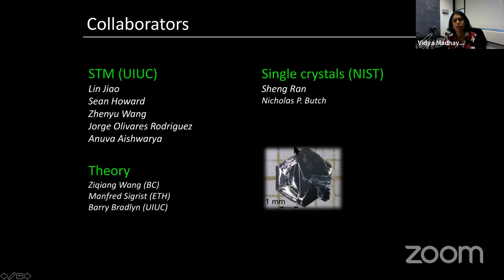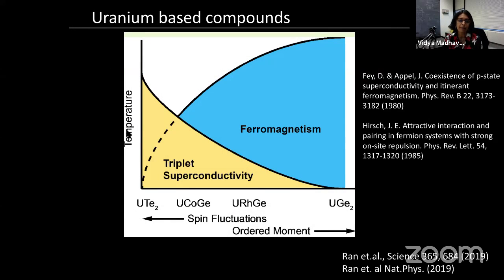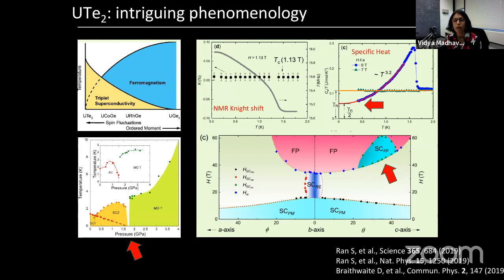The important thing here is that the material, uranium ditelluride, has been known for a long time as a heavy fermion metal. And it was only a couple of years ago that Sheng Ran and Nick Butch actually measured resistivity as a function of temperature below 1.2 Kelvin, and they saw superconductivity. So they made these beautiful crystals. They saw that it was superconducting, and that started a huge amount of excitement, mainly because uranium ditelluride is right at the borderline of being ferromagnetic. It's not ferromagnetic, but it's at the border of being ferromagnetic. And it has a lot of ferromagnetic fluctuations. So it's a prime candidate to realize triplet superconductivity. And in fact, there's a lot of work being done by Nick Butch, Jean-Pierre Paglione, and many other people that shows that this is indeed a triplet superconductor.